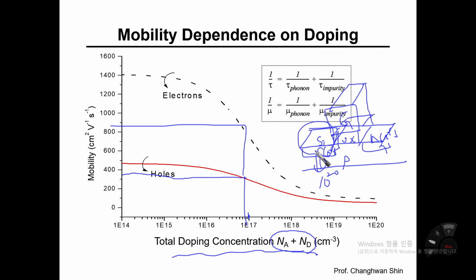But here the question is, this source region has been formed in the P-type substrate. Originally this source region has included tons of acceptors. However, the number of donors is more than the number of acceptors in this source region. So even though we are saying that this is an N plus silicon sample, so that is a very heavily doped N-type material, that would be governed by ND.